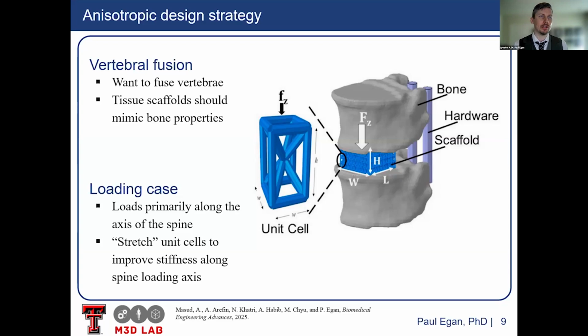And so our main application is going to be focused on bone fusion. Here you have a tissue scaffold implant that replaces the intervertebral disc, which is in between two vertebrae. And from those vertebrae, you're going to fuse it into a solid vertebrae over time. That's because sometimes those intervertebral discs degenerate and you need to partially or fully remove them. And so the common strategy is to do the fusion. What we're trying to do with the implants is create something that's optimal biomechanically. So for mechanics, that it survives the load and matches the stiffness of bone. And then biologically, that it has these small pores and surface area so tissue gets on the scaffold, but then grows over time so that you can generate bone.